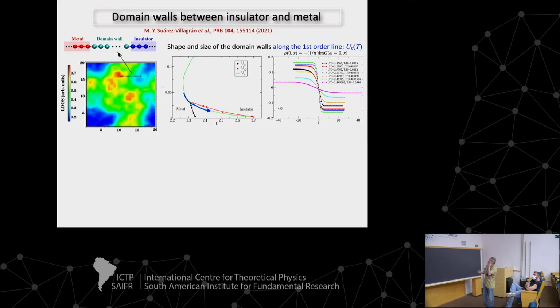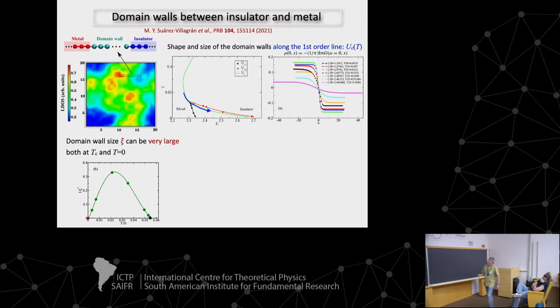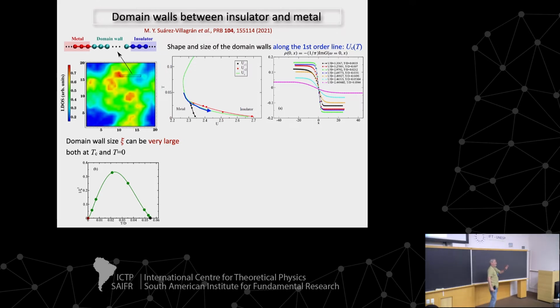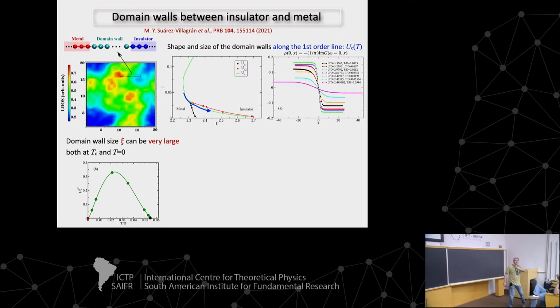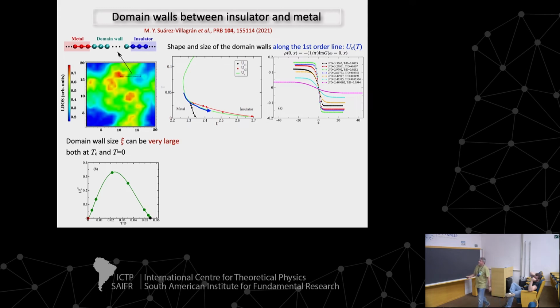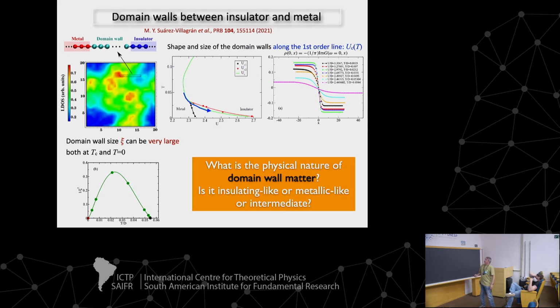And you can see the domain wall size becomes very large close to the critical point, as you expect, because they have a correlation length that's diverging at the critical point. And so this is the inverse of the size of the domain wall. It goes to 0. In other words, the domain wall becomes very large at the critical point. It also goes to 0 at 0 temperature. This is a feature of this particular treatment that I'm not going to go into. And there is physics in this divergence here, but I'm not going to go into it here. The important point is that if you're close to the critical point, you have large domain walls.